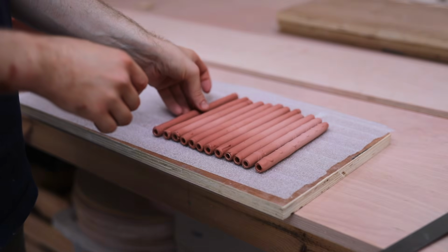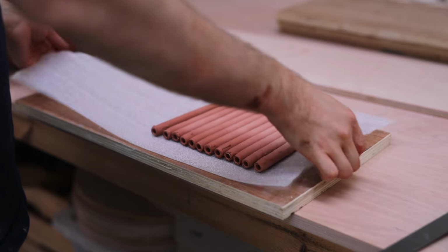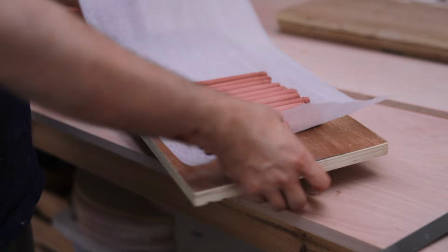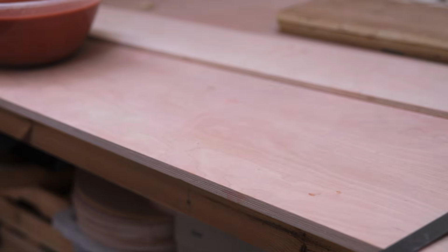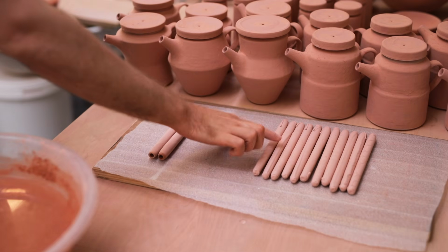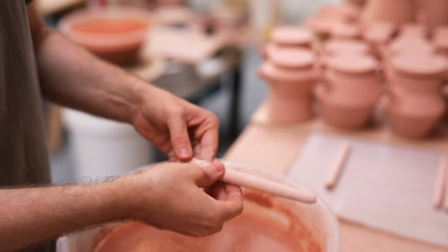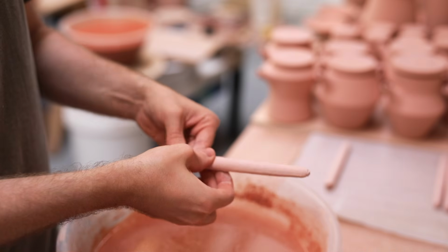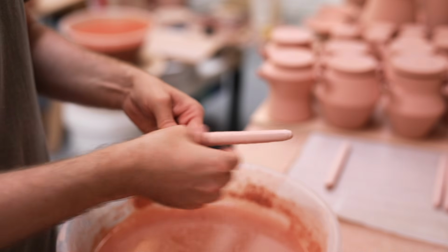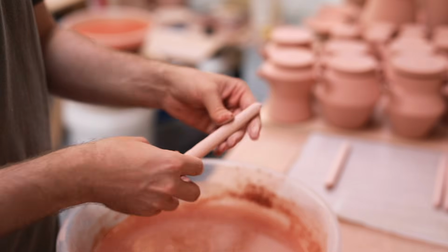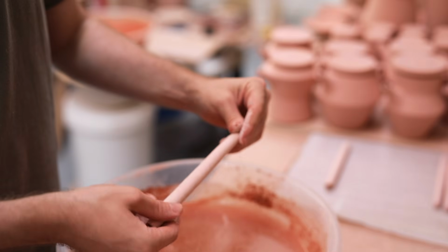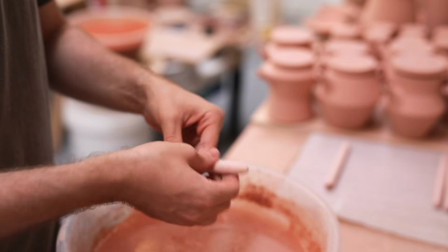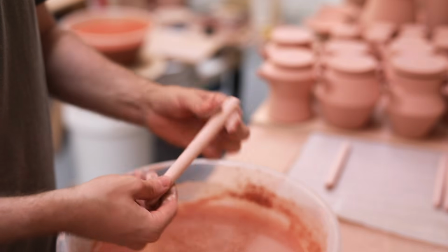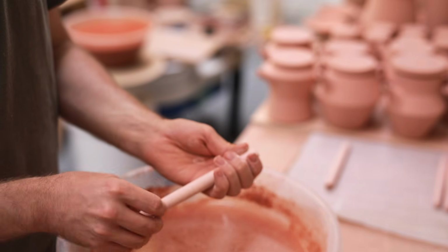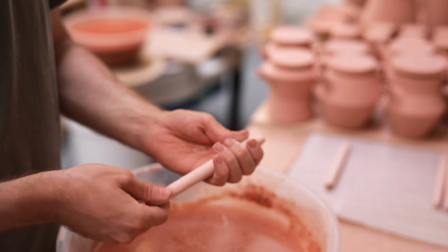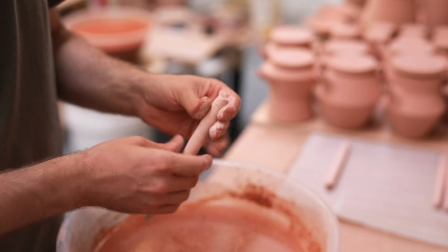As the pen bodies dry out, the surface of glaze becomes much more powdery, and for this glaze recipe in particular, it's easier to tidy up when they're at this stage, like you can see them here, although the fine layer of powdery glaze that surrounds them is very fragile, so I make sure not to hit it or chip the glaze away, but essentially I'm just rubbing away any excess drips or any thicknesses and fingerprints, as the neater the pen is at this stage, the better it'll look once fired.